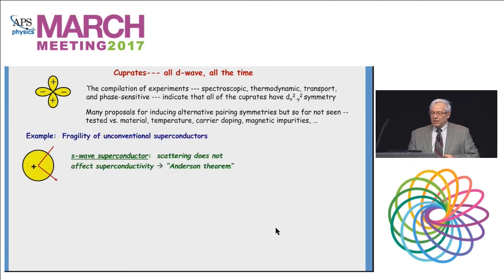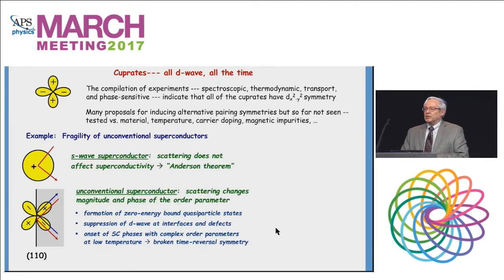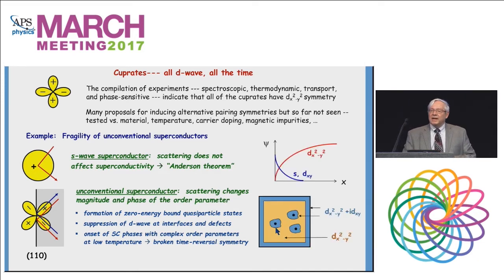We had a proposal for a long time we called the fragility of unconventional superconductors. It was believed that unlike in S-wave superconductors, where scattering doesn't do anything, the so-called Anderson theorem, if you look at the 110 interface of a cuprate, you should always get a sign change, a phase shift of pi, and that should give rise to the zero energy bound states at this interface. The thought was they would coalesce together, nucleate into a superconducting phase, and form some kind of a complex phase integral.